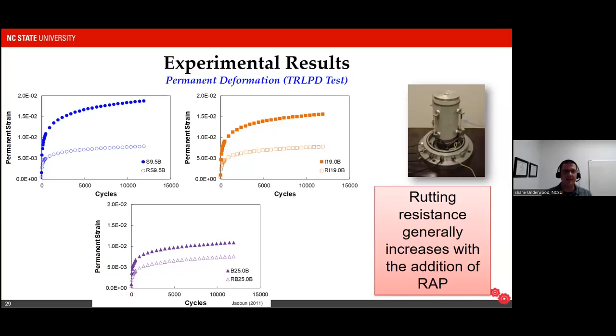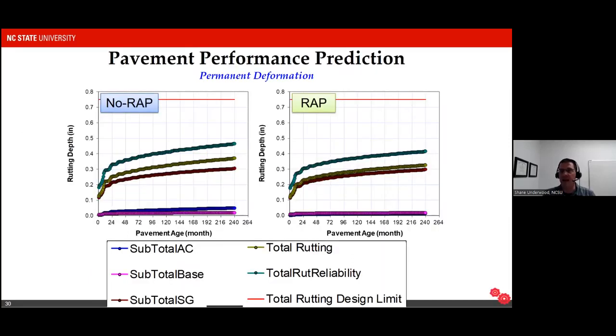Because we tested these particular properties of our asphalt mixture, we were able to use them in a pavement performance simulation. For us, we used the AASHTO Pavement ME software, at the time we did this known as the MEPDG, to predict the long-term performance of our pavements made with those materials. Here we're comparing the No-RAP versus the RAP, and you can see that the No-RAP pavement has more rutting, almost half an inch, versus the RAP-based mixture experiences a lot less rutting. This basically confirms the idea that adding the RAP would likely improve the rutting performance of our mixture, which is a good thing.